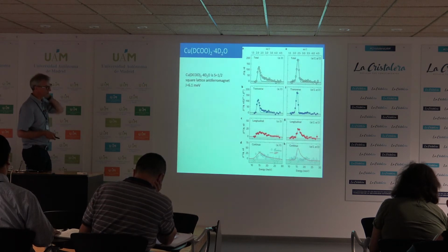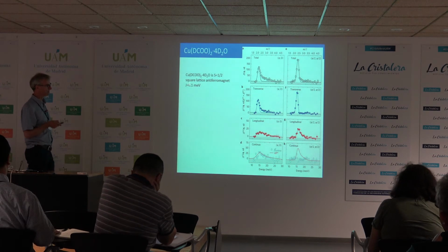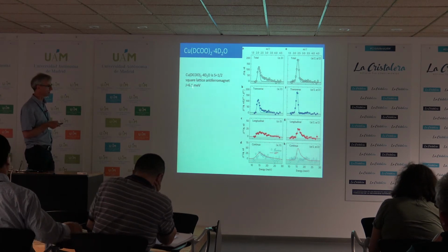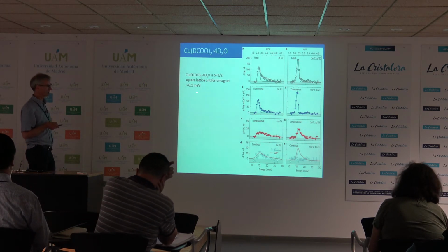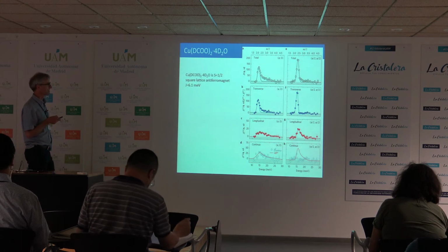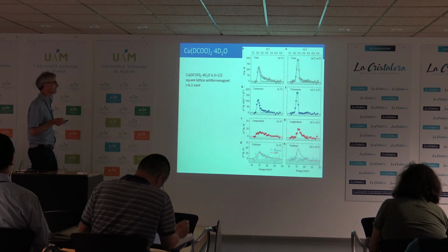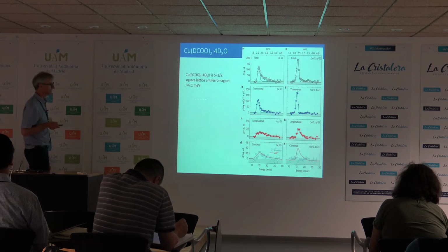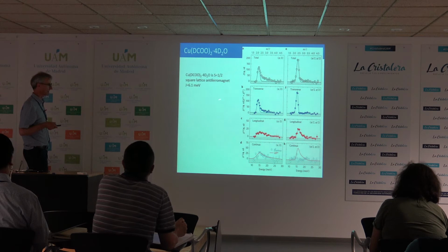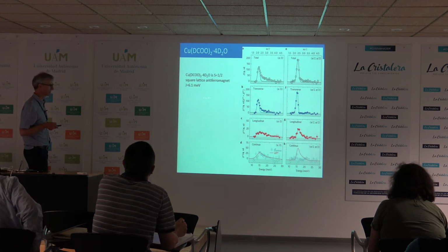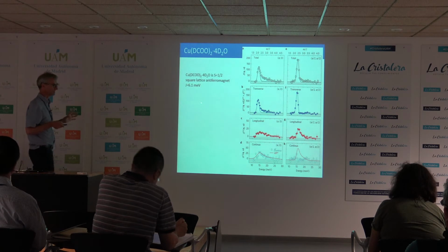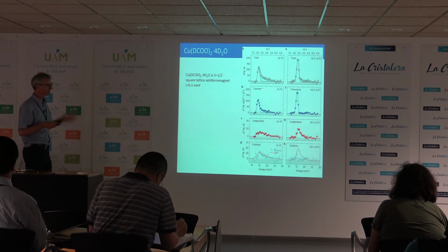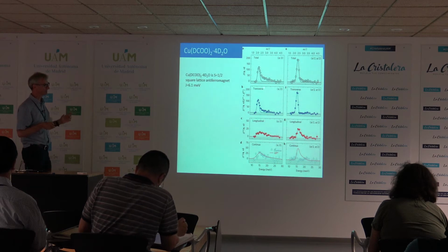So what we see here isn't unique to cuprates, though, actually. It's now known, well, in parallel, the work was going on square lattice spin-half antiferromagnets with much smaller exchange constants, such as deuterated copper formate here. I haven't put the reference. This is from various collaborations involving Henrik Rønnow and Desmond McMorrow, various people. They've been working on this compound here, which has got a much smaller J. It's also a square lattice with copper spin-halves. So they can see exactly the same effect. So it seems to be a generic effect of the spin-half square lattice.